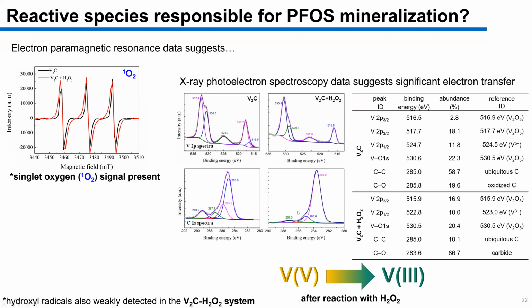You don't have to read this, but what it's basically saying is in the V2C sample, we start with vanadium 5 oxidation state. And then when we add hydrogen peroxide, the vanadium 5 is reduced to vanadium 3. And as a result, or a combination of this process, the carbon within V2C is being oxidized in this process. So vanadium is being reduced, the carbon within the V2C structure is being oxidized.